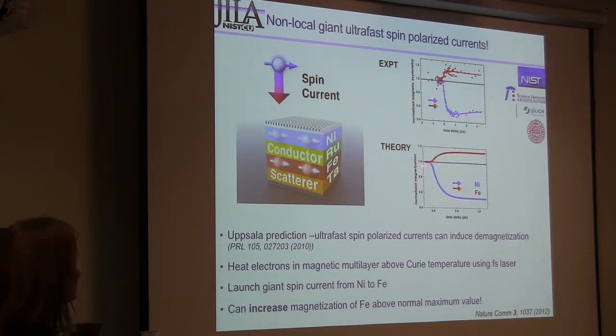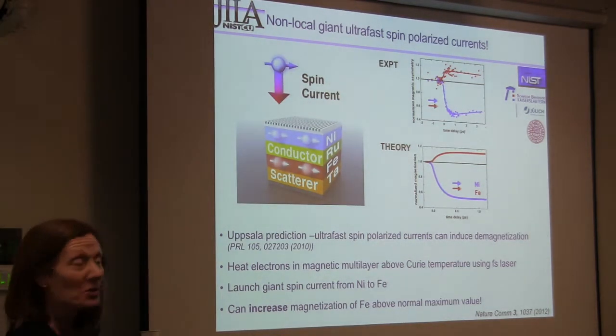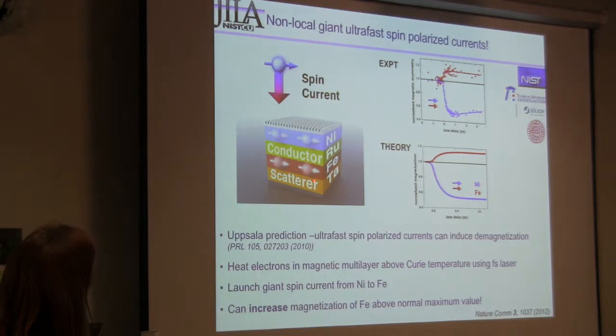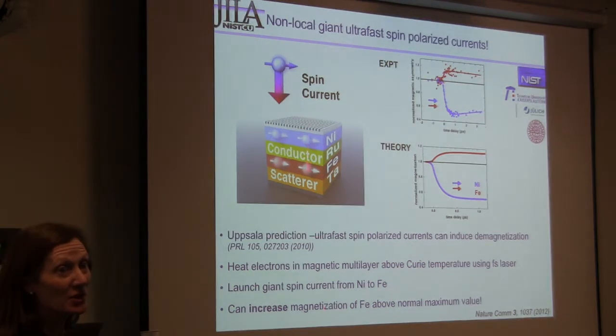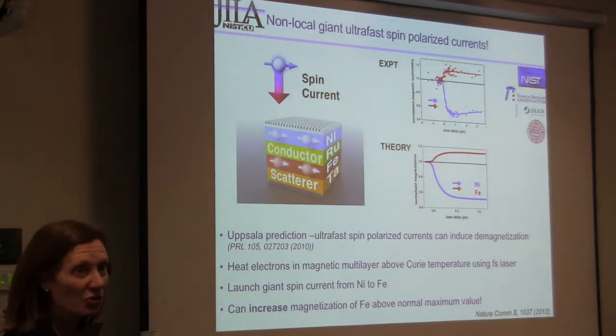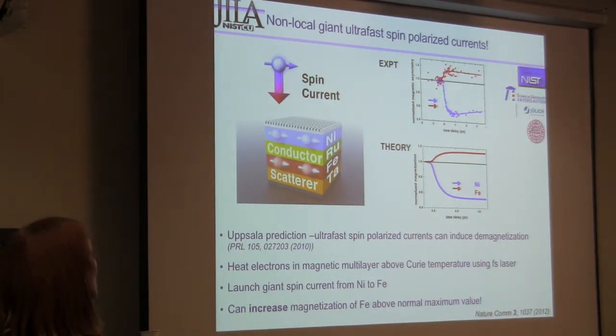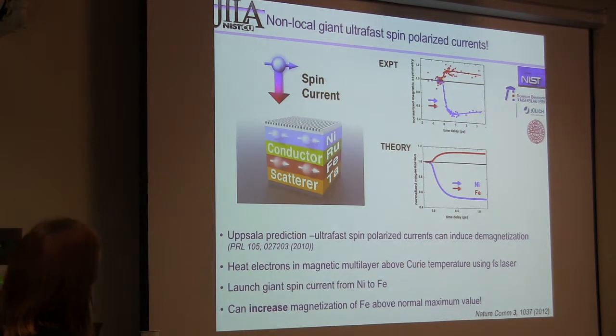And as luck would have it, it agreed perfectly with Peter Oppeneer's theory that the spins should move between one layer and the other, and of course they have to move down because they can't go up, so they reflect off the top. And that's why there's such a strong spin current, and that's why the magnetization in iron increases so much. But fortunately, Chan Do Lavarakia was writing his PhD thesis, and so we caught it just in time before we submitted the paper that we said maybe we should do a control experiment.